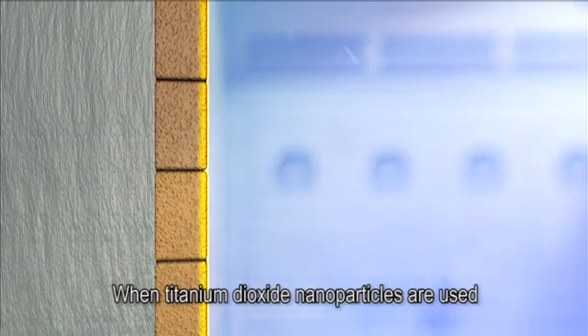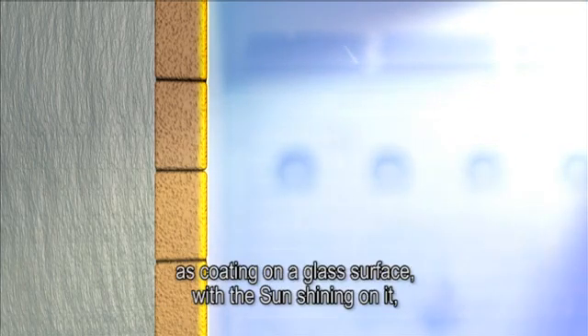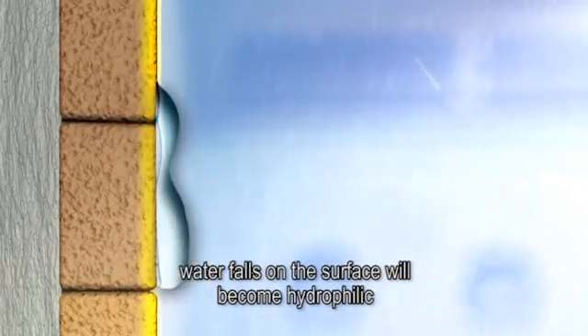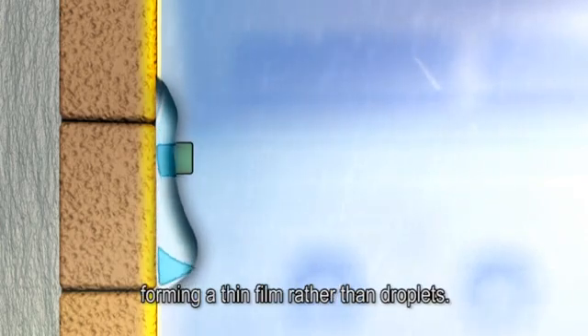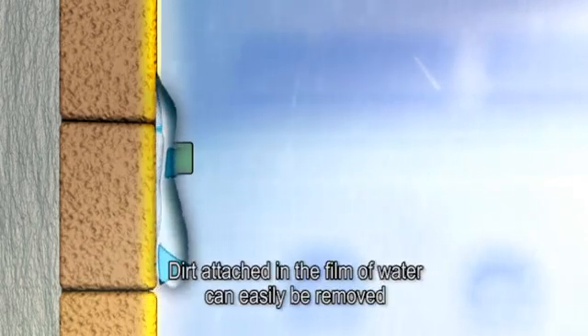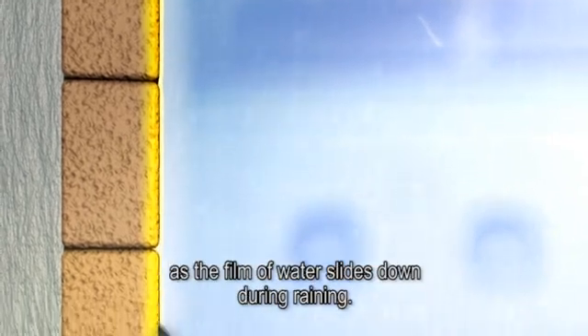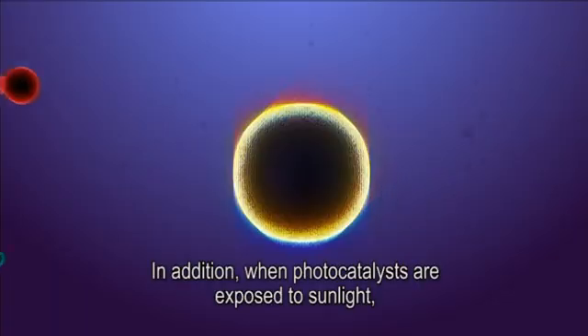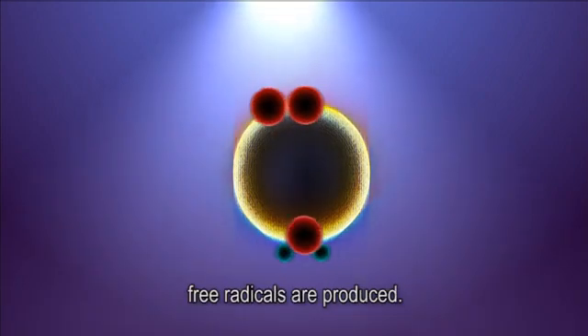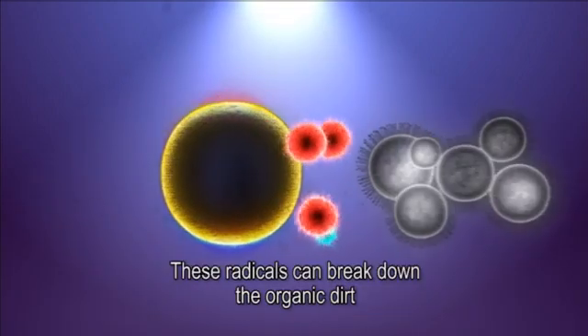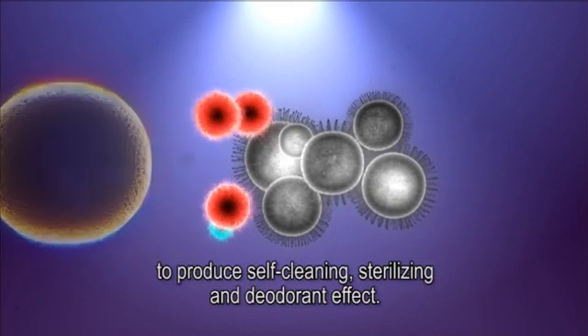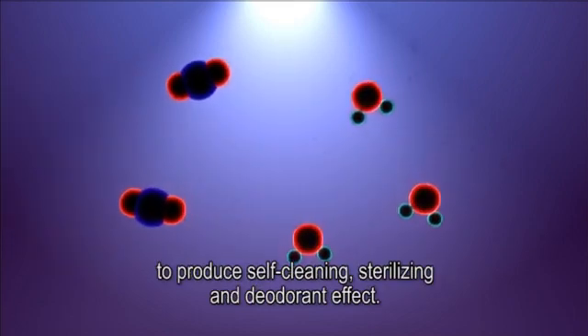When titanium dioxide nanoparticles are used as a coating on a glass surface with the sun shining on it, the water that falls on the surface becomes hydrophilic and spreads evenly on it, forming a thin film rather than droplets. Dirt attached in the film of water can easily be removed as the film slides down during rain. In addition, when photocatalysts are exposed to sunlight, free radicals are produced. These radicals can break down the organic dirt to produce self-cleaning, sterilizing, and deodorant effects.